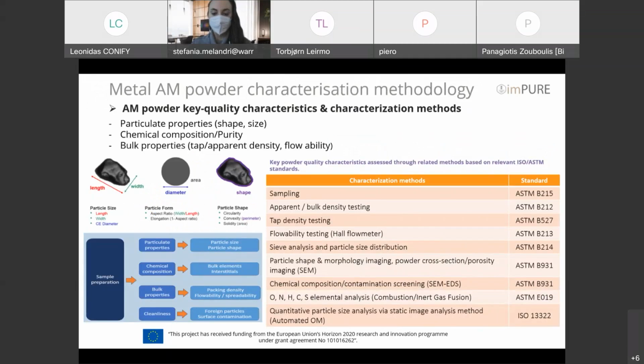So some of the methods that we use in order to assess the characteristics of our feedstock material: we look into particular properties such as the shape and the size, the chemical composition and the purity of the powder that we purchase. And of course, we look at the bulk properties such as tap and apparent density and the flowability. You can see on the right-hand side in the table all the different ASTM-based characterization methods that we run in-house in order to assess and screen all the different powder feedstocks. As I said, we look into particulate properties, the chemical composition, the bulk properties, and essentially the cleanliness of the powders. We look into shape and morphology extensively, such as the circularity, the convexity, and the aspect ratio of the particles. So next slide, please, Stefania.